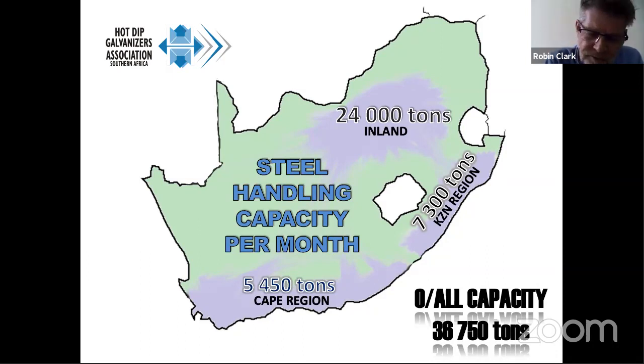And my calculations for these numbers were based on our members' capacity only. I'll discuss the others in a second. And this was estimated tonnage per hour times a single shift operation with an OEE of approximately 65%. We estimate in Gauteng, other plants may well be able to add another 2,000 tons per month. And in Cape Town, or the Western Cape specifically, there's probably a capacity for an additional 1,200 tons per month.